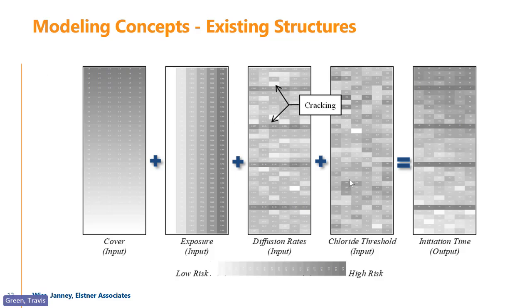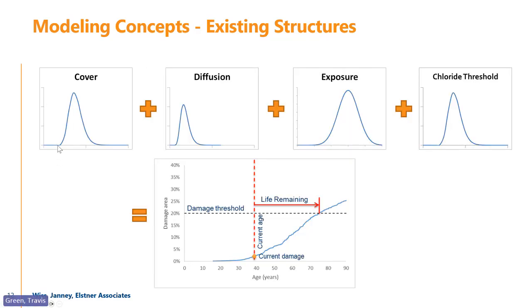And then generally we have chloride thresholds that are constant, but in this particular example we have different chloride thresholds. And so ultimately what we do there is we try to predict the initiation time, right? So in theory, you could have a bunch of different corrosion initiation times depending on all these variables, right? So to go back to that point, you could have, for example, low cover, high diffusion, high exposure, low chloride threshold, and you end up with a curve that's very steep. Does that make sense? And then if you look at another set of parameters, that's how we build these curves.